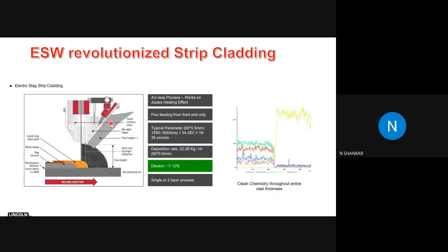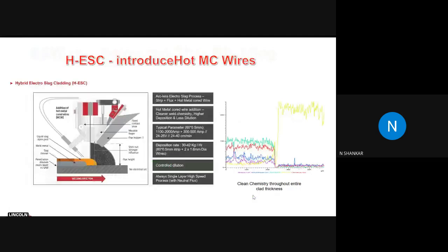depositions basically. You can do a single or a two-layer process with this electroslag strip cladding, and you get a clean chemistry when you do it with an ESW process rather than with the SAW process actually. So that is the advantage of electroslag strip cladding. Now I'll come to the hybrid part of it.